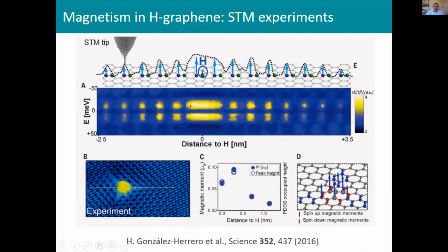of plot for the positive electron doping and hole doping. Here in this case, the doping I am referring to the current in the STM. So one important thing here is that as the theory predicts, the magnetic moment is not localized at the site of the defect, is localized around the defect, but mainly in the sublattice corresponding to the same sublattice where the impurity is absorbed.